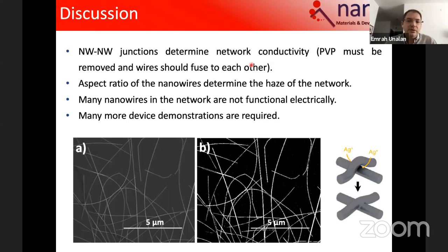But once you have the junctions, there comes the scattering, and there comes the source of resistance. So this resistance has two folds. One of them is that in the junction region, you have the PVP. So PVP is, for silver, a dispersant and a directionality agent. So that needs to be taken care of.